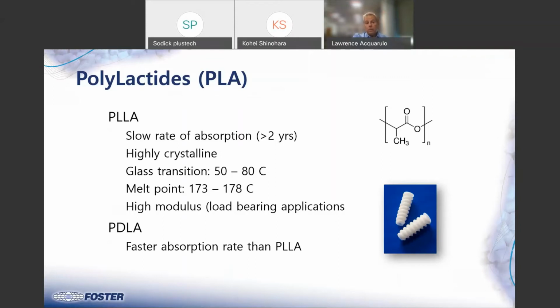Highly crystalline, with a medium glass transition temperature. The melt point is not high, which is good, so it's very processable. And it has very good load-bearing applications, and that's one of the reasons it's finding a lot of use in these orthopedic applications. The D version of it has a lot of the same attributes, but a faster absorption rate. So why you would use one or the other would be based on the absorption.